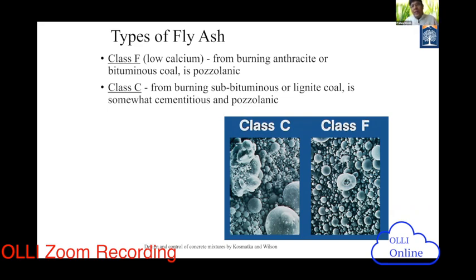Class F has low calcium. We know cement has more calcium products. So class C, having more calcium products, becomes more cementitious and less pozzolanic, whereas class F, having low calcium, is more pozzolanic than cementitious. So different chemical compositions are at play, and accordingly we use the replacement level wherever we want more. These are the scanning electron microscopy pictures of class C and class F.